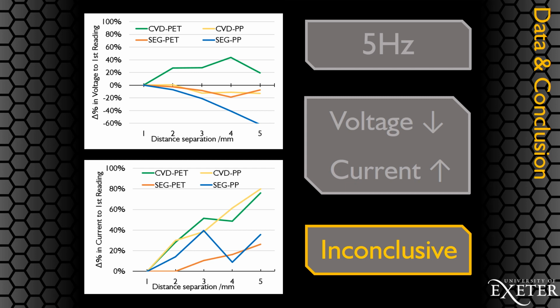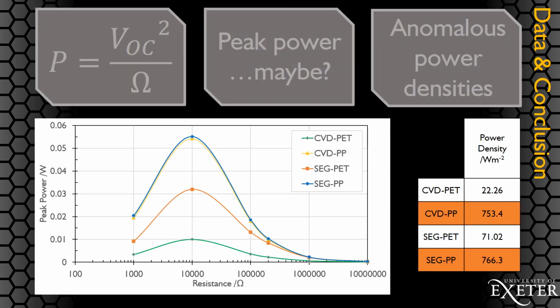It is worth noting, however, that prior papers looking at PDMS TENGs with aluminium electrodes saw a positive trend for both current and voltage at greater distances. In the last set of graphs, we attempt to calculate the TENG's peak power and power density. Peak power is found using Ohm's law and the power formula, where power is equal to the open circuit voltage squared divided by the resistance. This was achieved using a variable resistor across the TENG ranging from 1 kΩ to 10 MΩ, with voltage readings being made each time. The chart indicated the peak power occurs within the 1 kΩ to 100 kΩ range. It's not yet clear if 10 kΩ is the peak, as further data points are needed in that area.